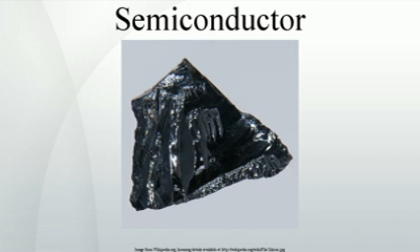A 1 cm³ specimen of a metal or semiconductor has of the order of 10²² atoms. In a metal, every atom donates at least one free electron for conduction, thus 1 cm³ of metal contains on the order of 10²² free electrons, whereas a 1 cm³ sample of pure germanium at 20 °C contains about 4.2 x 10²² atoms, but only 2.5 x 10¹³ free electrons and 2.5 x 10¹³ holes. The addition of 0.001% of arsenic, an impurity, donates an extra 10¹⁷ free electrons in the same volume, and the electrical conductivity is increased by a factor of 10,000. The materials chosen as suitable dopants depend on the atomic properties of both the dopant and the material to be doped.